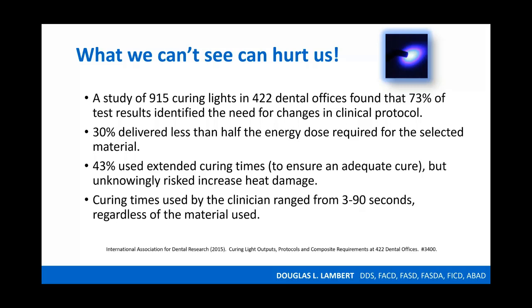And 43% of the offices used extended curing times, obviously to try and ensure an adequate cure, but unknowingly, because those extended curing times weren't monitored, they risked the increased heat damage that could cause some pulpal damage and/or post-op sensitivity for the patient. And then curing times used by the clinician range from 3 to 90 seconds, regardless of the material used. So there really wasn't a roadmap for these dental offices to know where to go. How much should I cure the material I'm using, for how long, and with how much energy?